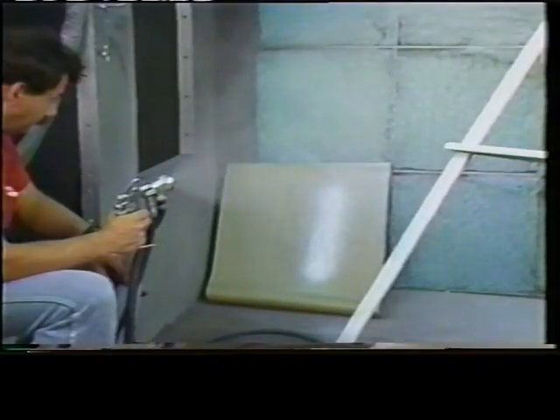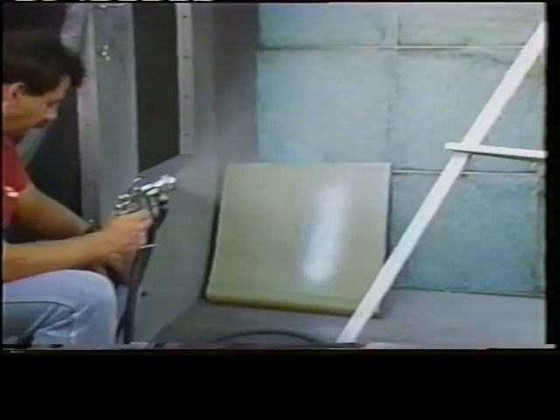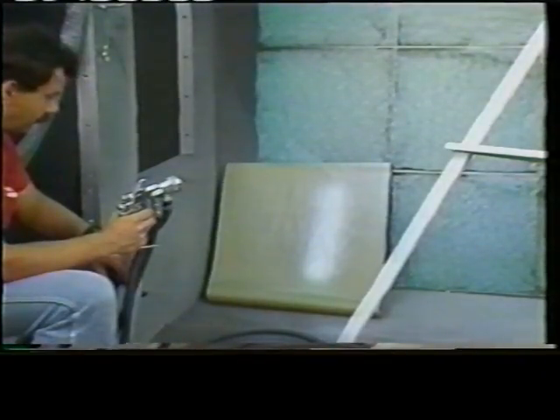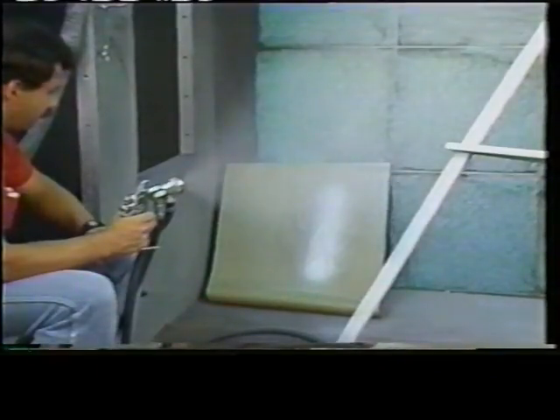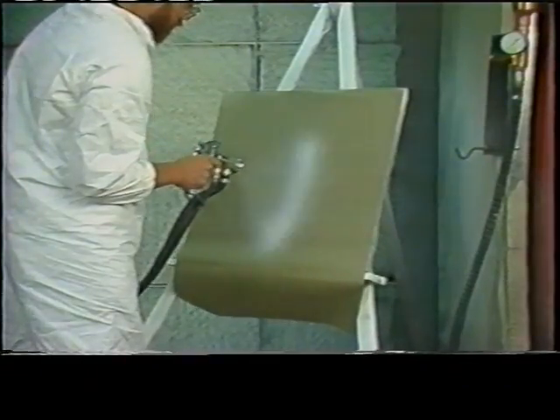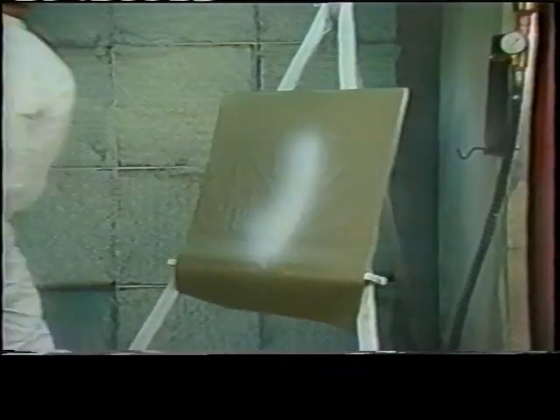As with the other air atomizing systems, the Can-Am applicator performed well in the simulated automatic line testing. No problems in spraying or atomizing were noted. The slight crescent that developed in the spray pattern undoubtedly resulted from airflow in the booth, not from any deficiency in the waterborne coating. The tip of the spray gun remained quite clean.